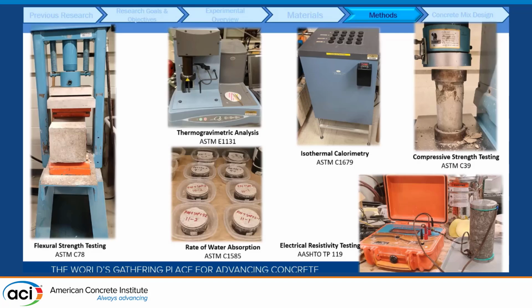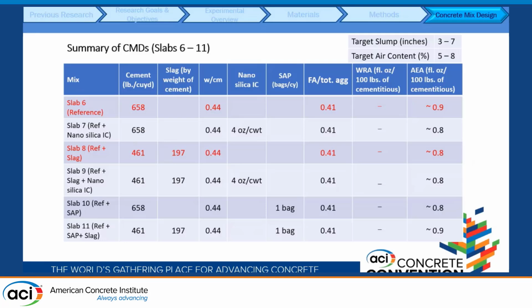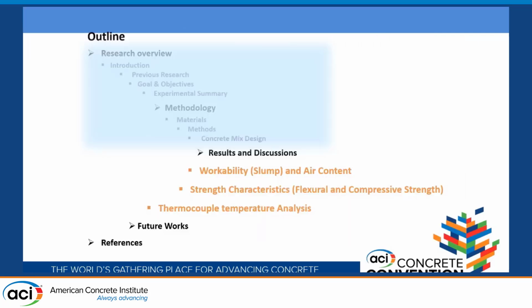The stipulated methods by the ASTM were used in most of our lab testing. And for the mix design, our target slump was 3 to 7 inches, and the target air content was 5 to 8% at a constant water cement ratio of 0.44. And for those practical purposes, no superplasticizer was used. And for the batching of the SAP, we added one bag of the SAP for 1 cubic yard of concrete.